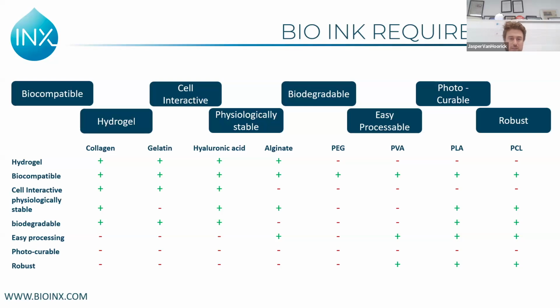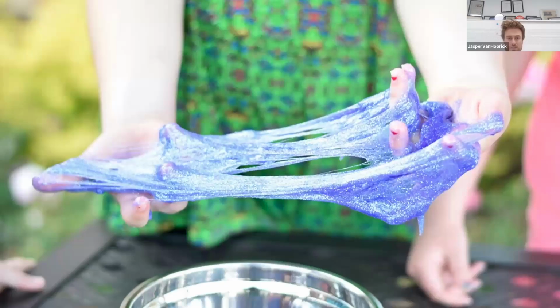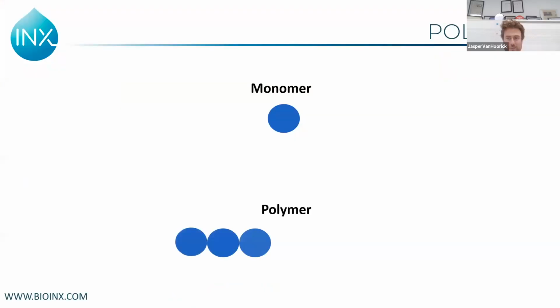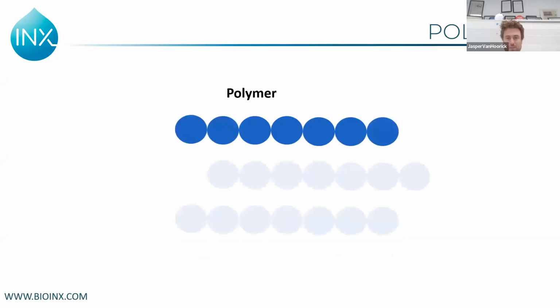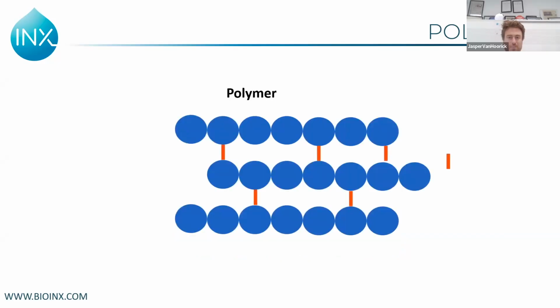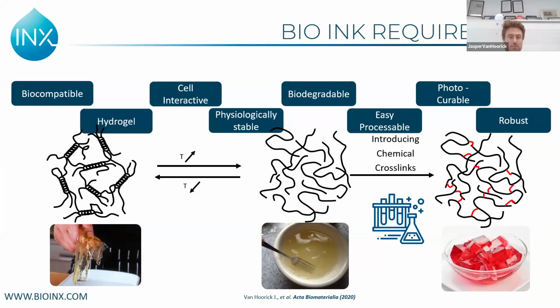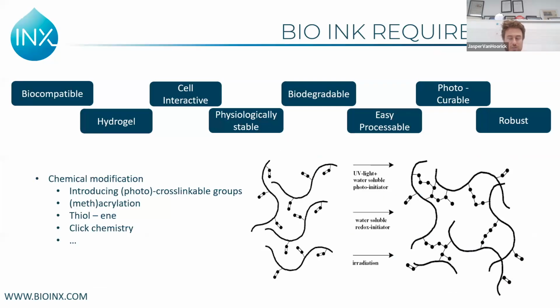Because what happens with most of them, if you put them into the body, the hydrogels, they would dissolve, they would lose structure. So we need to tackle this chemically. So going from this polymer, we can also go into polymer networks by introducing crosslinks in between them. So we can cross-link these materials, which makes them insoluble. If, for example, you look at gelatin, you can transform it into GelMA, and then you have a polymer network which can no longer dissolve at body temperature. You can do this via introducing different chemical functionalities. Acrylates, methacrylates are very popular, but you can also use other groups like thiol-ene or click chemistry or enzymatically linkable groups, because basically you need this network.